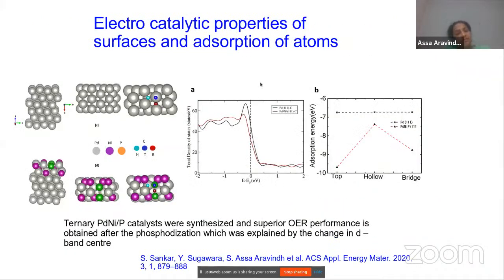Now, coming to catalysis applications, a lot of noble metal surfaces are used for catalysis. And in this study, again, done in collaboration with Tokyo Tech, Japan, they were using this palladium catalyst, and then they were alloying at the surface, which was enhancing the oxygen evolution reaction performance.